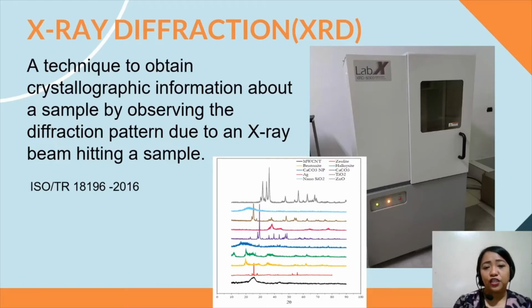X-ray diffraction analysis, or XRD, is a technique to obtain crystallographic information about a sample by observing the diffraction pattern due to an X-ray beam hitting a sample. Shown here is an example of XRD data. So you can actually identify the mineralogy of your material based on this data.